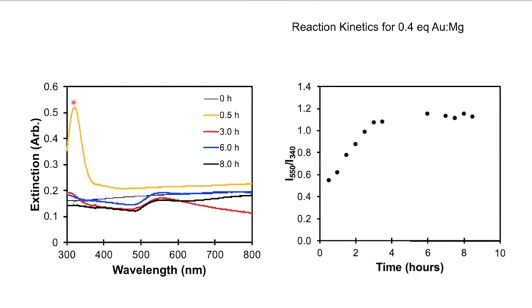because your gold salt has a big absorption here, just higher than 300 nanometer. And then the gold particles start to absorb here at about 550. So by looking at the ratio, we can look at the rate of consumption of the gold ions and them turning into gold particles. And the reaction is relatively slow. And despite this amazing driving force, right, it still takes us about 3 hours to reach our final product.